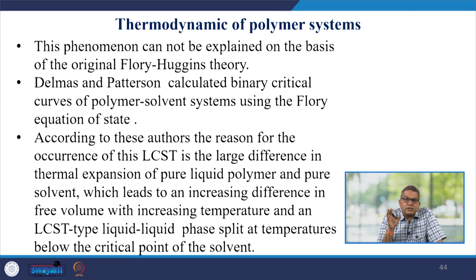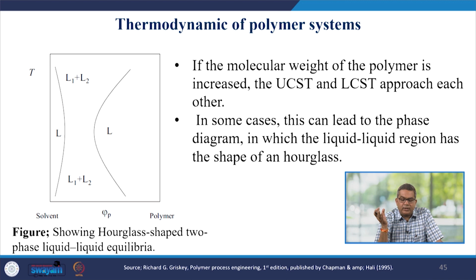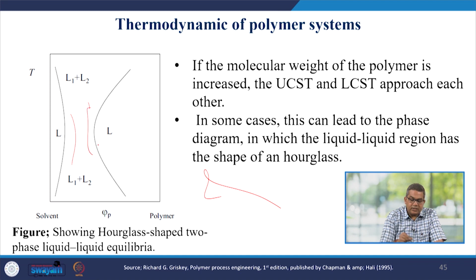So, other co-workers, Delmas and Patterson, calculated binary critical curves of polymer-solvent systems using the Flory equation of state. As per these authors, the reason for the occurrence of LCST is the large difference in the thermal expansion of pure liquid polymer and pure solvent, which leads to an increasing difference in free volume with increasing temperature, and LCST type liquid-liquid phase split at temperatures below the critical point of the solvent. So, here you see that if the molecular weight of the polymer is increased, then UCST and LCST approach each other. Here you can see clearly.